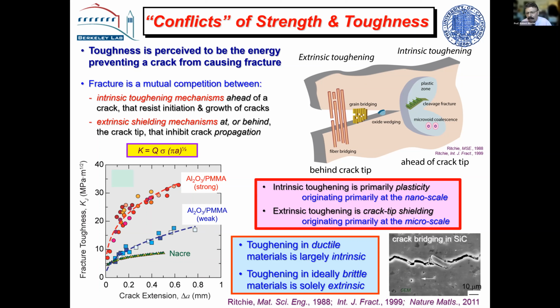That can lead to what's known as an R curve or resistance curve. And if we look at the fracture toughness, I'm using a stress intensity here, which is, as you know, the amplitude of the stress field at the crack tip. And we plot it against crack extension. You get an R curve if you have a relatively tough material. And the initial point of the R curve is the crack initiation toughness, which people measure, K1C, J1C. It's a readily measured parameter.